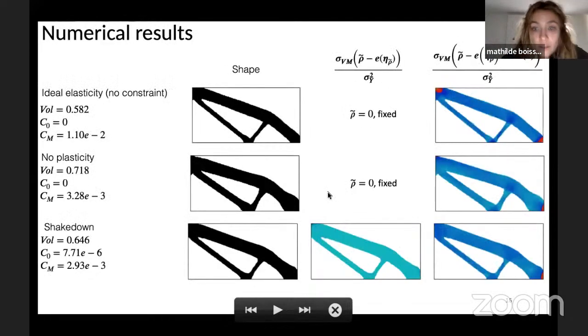And here are the results. So that's the cantilever we had before. Here it's ideal elasticity. So that's what we said: very thin bars, but we have some trouble with plasticity. When we consider von Mises constraints, so we don't want any plasticity here, we see that the bars are thicker. And well, we remove plasticity.